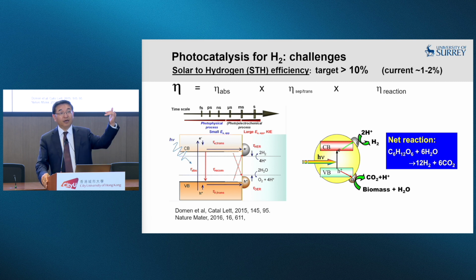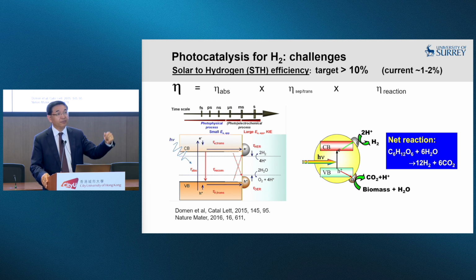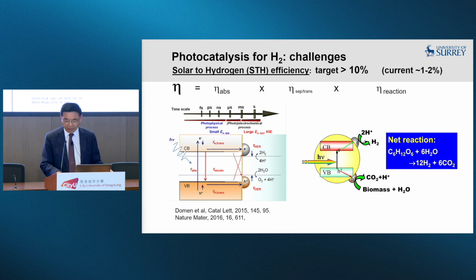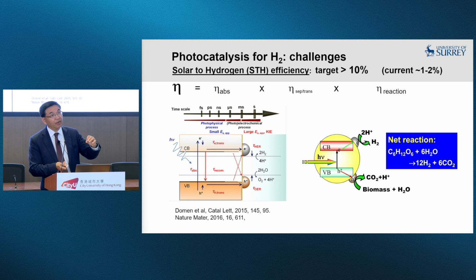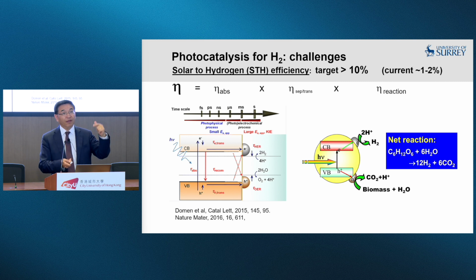So the photon irradiation and the separation of the electron-hole happens very fast, at the femtosecond scale. And of course, the separation and transfer and then surface reaction happen at millisecond to second scale. And of course, from the electronic structure level, to the atomic structure, to the nanoparticle level, and then to the reactor level.